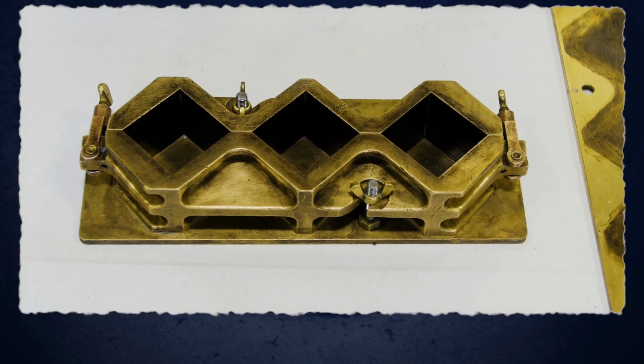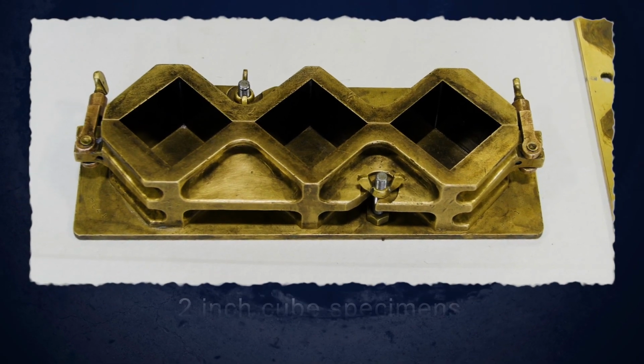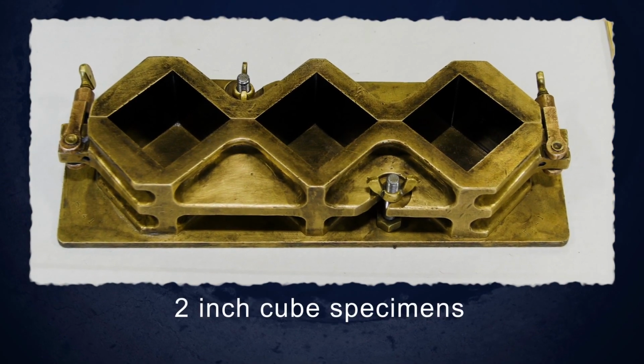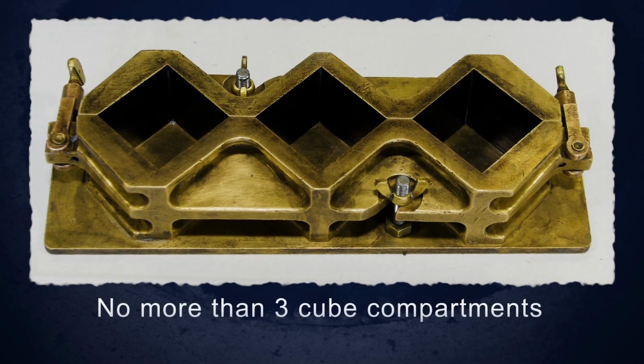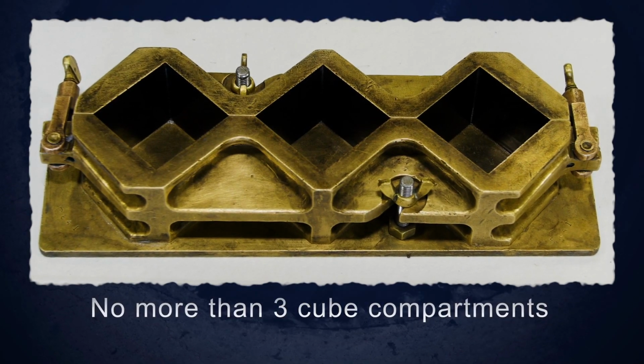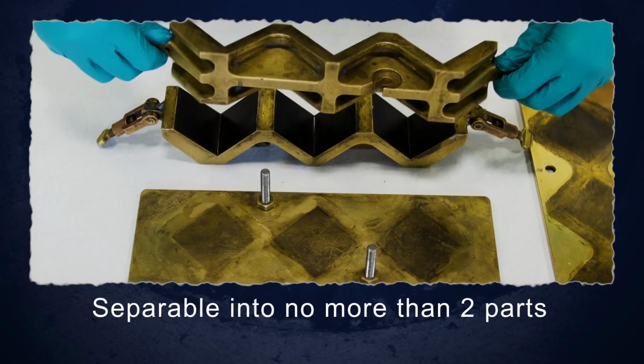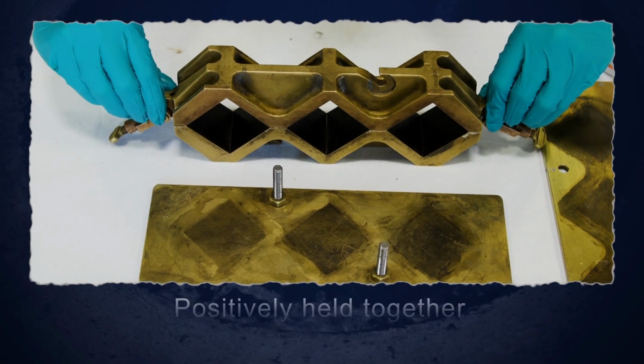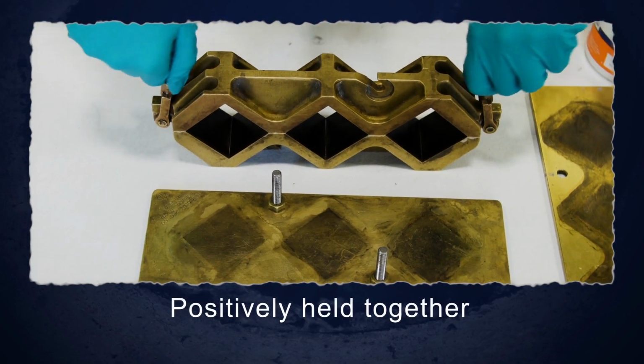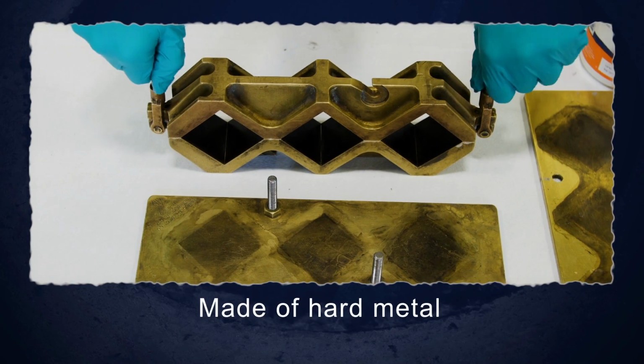This test requires the use of specimen molds. The 2-inch cube specimen should be tight-fitting and have no more than 3 cube compartments. Mold should be separable into no more than 2 parts and should be positively held together. The mold should be made of hard metal not attacked by cement mortar.